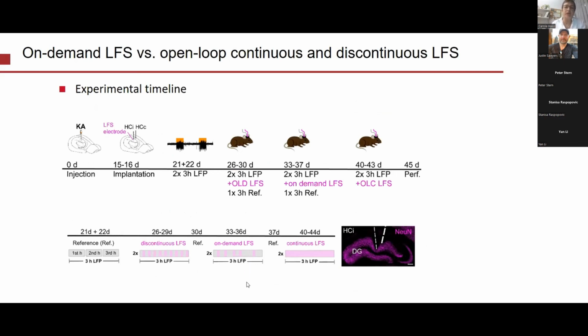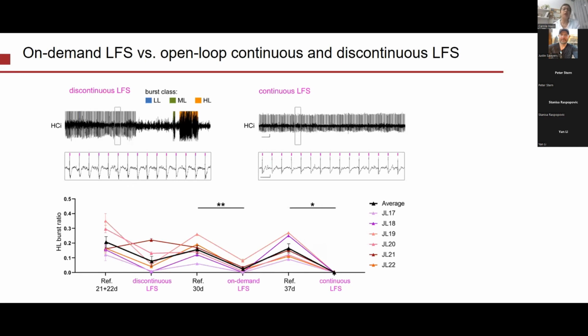And that was done by Enya in collaboration with a master student. So in the same animal, the different stimulation paradigms were applied and compared in their efficacy. And what we found, and that was very nice to see, is that the discontinuous LFS, that means 10 minutes on, 10 minutes off, was to some degree efficient, but not as strongly as the on-demand closed loop or the continuous one. So the best comparable stimulation paradigms, so to speak, are the continuous and on-demand. So that was very exciting.